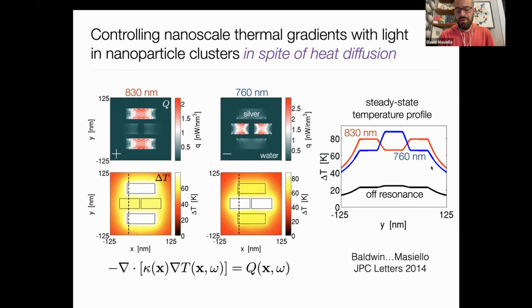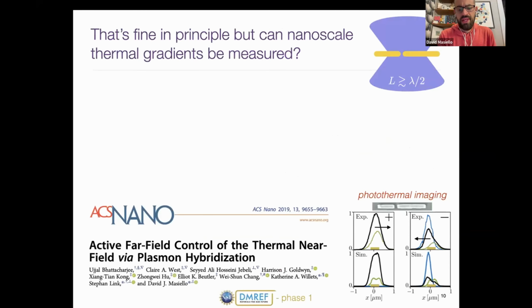So this is all great in principle, but does it work in practice? And so that started a long-term collaboration with Stefan Link and Katherine Willets, both of whom have given or will give seminars as part of the seminar series, where we actually nanofabricate. But when I say we, I mean them. I'm a theoretician. I didn't go into the lab and do any of this myself, but they nanofabricated a heterorod dimer, the lengths of which were just larger than the diffraction limit of light. And they did photothermal heterodyne imaging and imaged the point spread function as a function of driving at either the bonding resonance wavelength or the anti-bonding resonance wavelength. If you can see my hands, that's the bonding and that's the anti-bonding in this rod dimer structure.